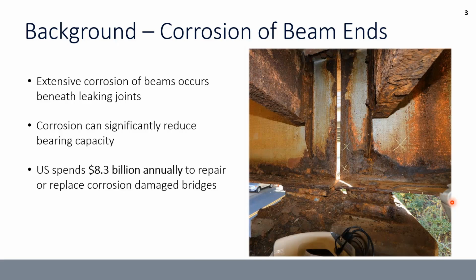It's really not a bad sign for steel. It's a bad sign for leaking deck joints. Leaking deck joints are the primary source of major corrosion on both steel and concrete bridges. In this case, a steel bridge. And this photo shows a typical beam end that we see for older bridges, especially beams that are on the fascia near the gutter line where most of the water is coming through the joints.